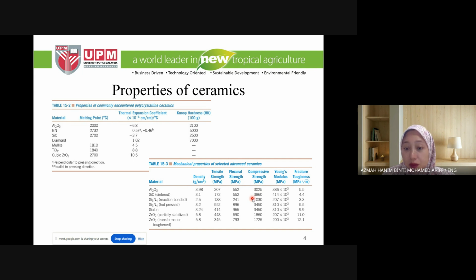So if you wanted to compare the properties, you can see that, for example, alumina tensile strength is only 207 megapascal. Flexural strength is 552 megapascal. But when you look at the compressive strength, it is 3025 megapascal. It is more than double, triple, quadruple, maybe five or six times. Basically, it's really high compared to the tensile strength and the flexural strength properties.